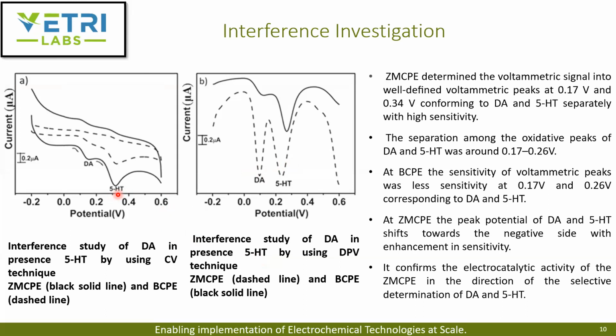To further identify the interference, they used differential pulse voltammetry. As you can see, the bare carbon-based electrode had very low sensitivity corresponding to dopamine and 5-HT. Whereas for the zirconia modified carbon-based electrode, which is the dotted lines over here, the peak potential shifted towards the negative side, and there was also enhancement in the sensitivity of both dopamine and 5-HT. This confirmed that there was no interference, even in the presence of dopamine, in the selectivity and sensitivity towards serotonin.